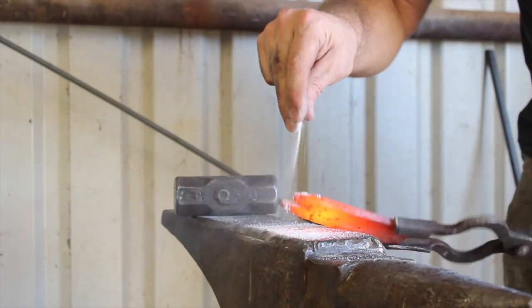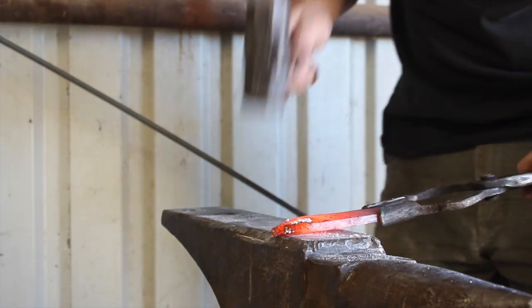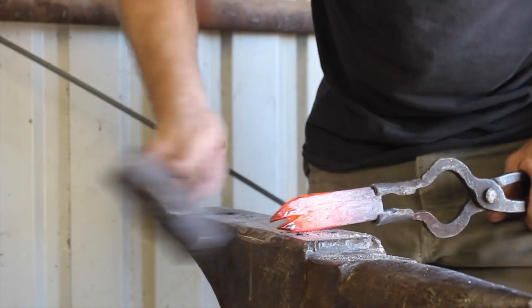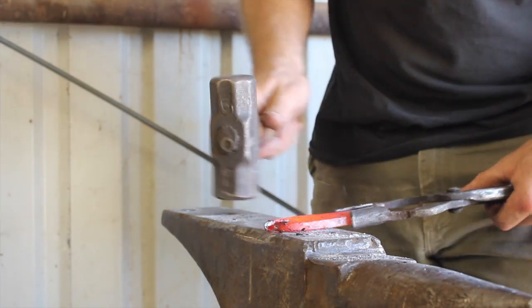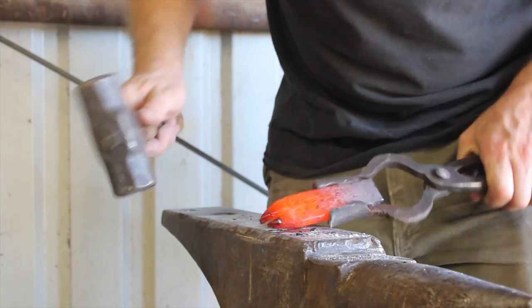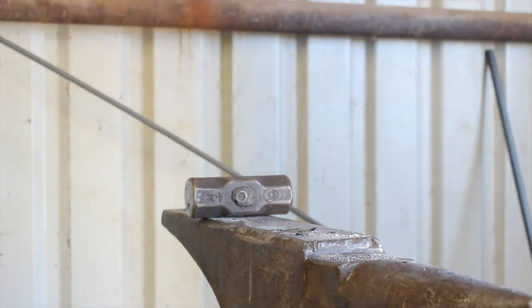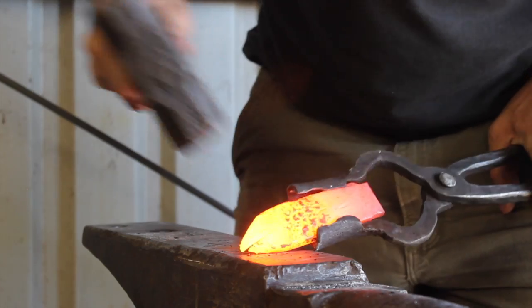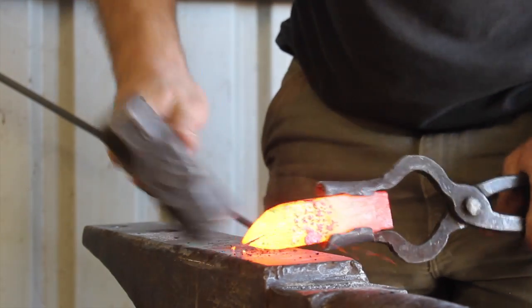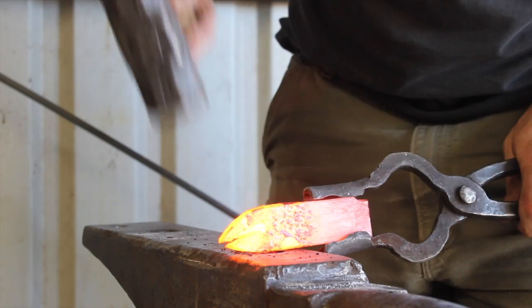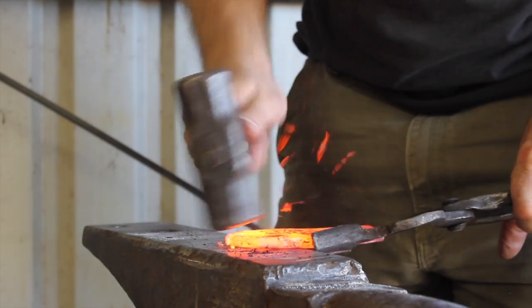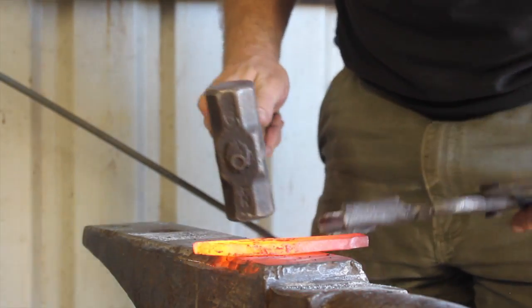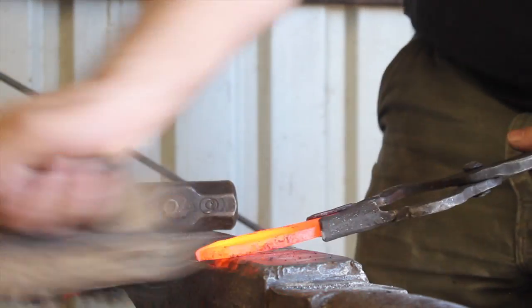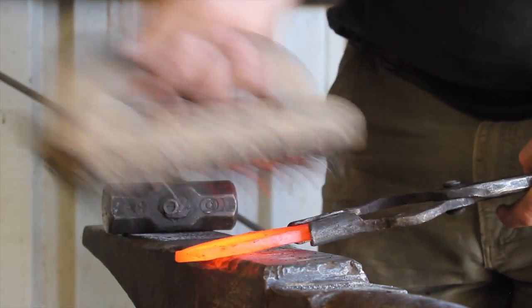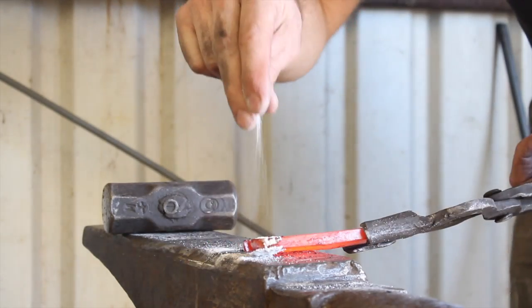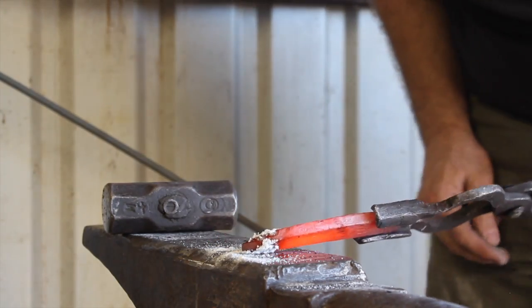So what's going to happen is we're going to weld this V together, and as we go, it's the best case scenario for an open atmosphere forge weld like this, where we're going to be able to easily force out the flux and impurities as we close it up, and keeping that flux on there. So those two sides of the V that are coming together, those both have a radius on them, like I mentioned a minute ago. And that's important because that makes sure that at no point is there going to be a void in between those two